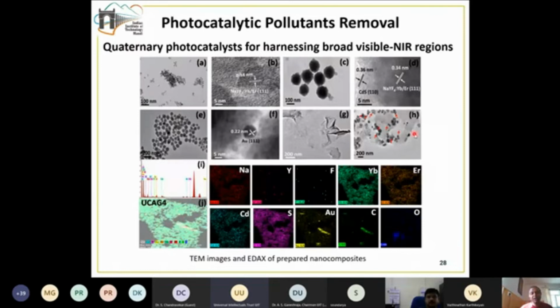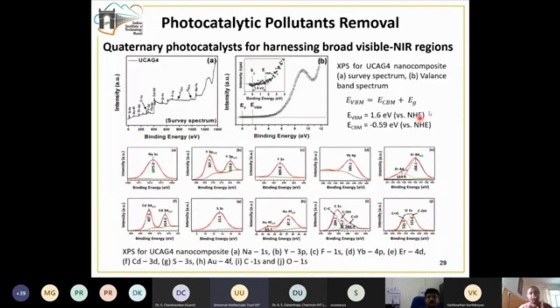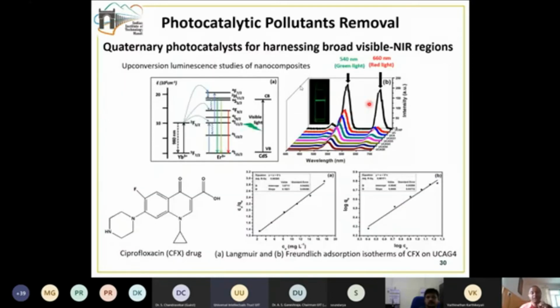Then we did a very detailed XPS characterization, and from the XPS also we were able to experimentally determine the valence band maximum position. So we did UPS, a special type of XPS, wherein we could experimentally determine the valence band maximum position. And then we did the normal XPS to understand the oxidation state and the other properties of this material. And since this is an upconversion nanoparticle, we also studied its upconversion luminescence, wherein we could clearly see the green light emission here. There is also a red light emission, but that is suppressed, and green light emission is the predominant thing.